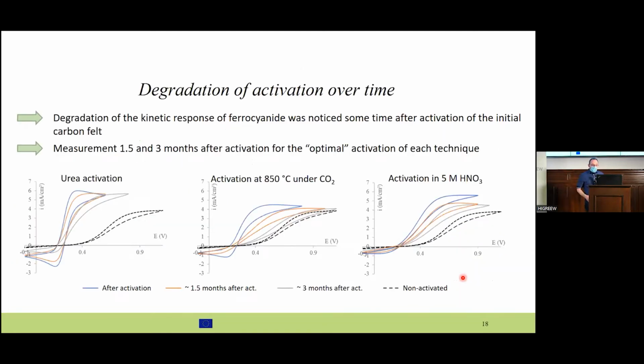What we have to be aware of, what we need to take care of, is the stability of the activation. This is an example. Because the measurement we do is very accurate, probably we could not see this degradation at the macro scale, but at the microfiber scale, we can see that here is before activation. We activate, and with time, the signal is going back to the right, to the less active situation.